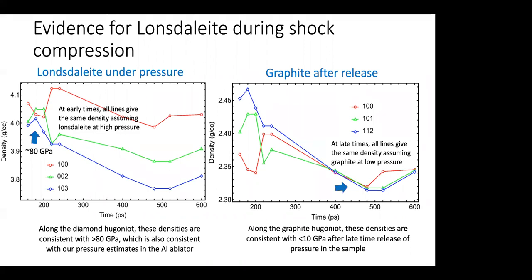So I have two structures here. One is the Lonsdaleite on the left, the other is graphite. One thing that is important to note about these experiments, we may well be seeing an intermediate here. The reason is that while the sample is under compression, we believe we're seeing Lonsdaleite, but once that pressure is released, it seems to transform back to graphite. And this could also potentially be consistent with the original hypothesis of Bundy, that they may be seeing this layered bilayer diamond form, which is not an equilibrium form, and we would not expect that to form a diamond as well.